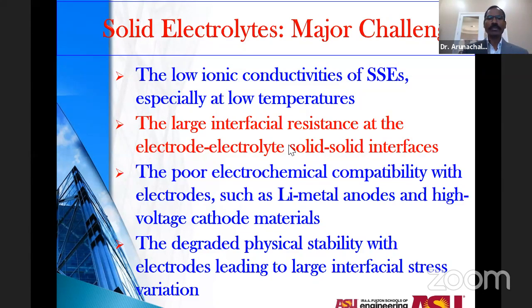In addition to the interfacial resistance, solid electrolytes could also lead to electrochemical compatibility issues. Even though solid electrolytes can have a huge electrochemical stability window, there could be compatibility problems with lithium anodes and other high voltage cathode materials. In addition, there could be some stress associated with the physical stability of the electrode-electrolyte interface. If they degrade, this could lead to stress and then maybe breaking up or decreasing the integrity of the electrode-electrolyte structure in all solid-state batteries. As I have highlighted in red, interfacial resistance is one of the major issues.